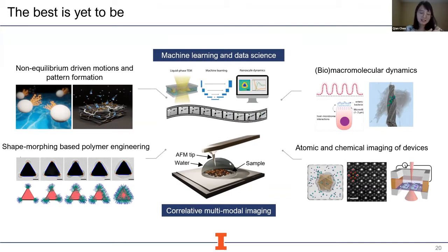So in terms of the exact misalignment angle, we couldn't really resolve it in experiments, but we could learn some insights from simulation. In simulation, it turns out it's actually quite randomized. It's actually due to this randomization that we can have a circularly shaped cylinder leading to this final crystallization. Yeah. So in your liquid TEM, it's not possible yet to do this, not enough time or maybe dose to do diffraction?